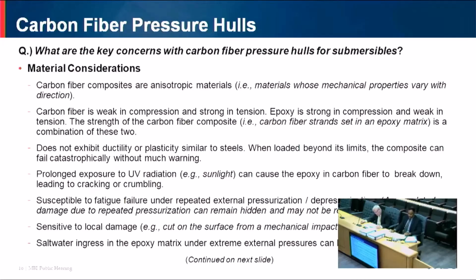So then the next thing is prolonged exposure to UV radiation can cause the epoxy to get damaged. So what happens is the epoxy, in some cases, you add something called a UV stabilizer. It's a chemical that's added in the epoxy, and that protects the epoxy from UV radiation. In some other cases, you can have a gel coat or a top coat which is placed on the epoxy. For example, you can have a polyurethane coating, and that protects the epoxy from the damage caused by UV radiation or the sunlight. Okay? So if you don't have this protection and you expose the carbon fiber composite to sunlight, the UV radiation will degrade the mechanical properties of the composite.